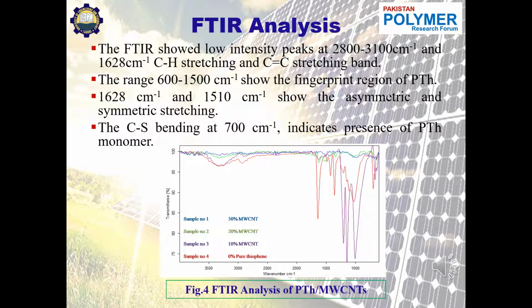Moving to the characterization of synthesized nanocomposite, first of all, I would like to discuss the FTIR analysis. The FTIR analysis was done to check whether the chemical bonding of polythiophene with MWCNT has occurred or not. The FTIR showed a low intensity peak at 2800 to 3100 per centimeter and a peak at 1628 per centimeter, which shows the carbon-hydrogen bond stretching and carbon-carbon double bond stretching. Secondly, the peaks shown in the range of 600 to 1500 per centimeter showed the fingerprint region of polythiophene.